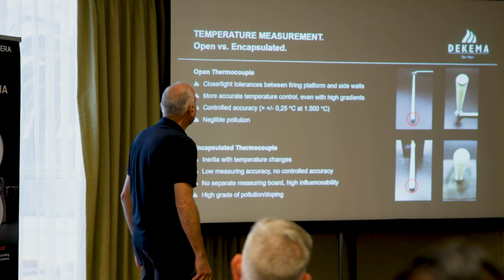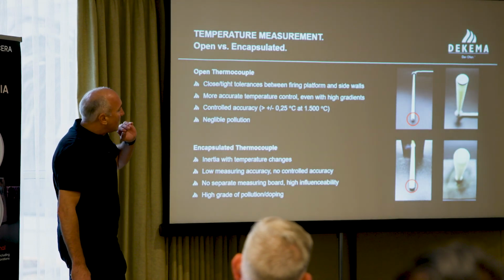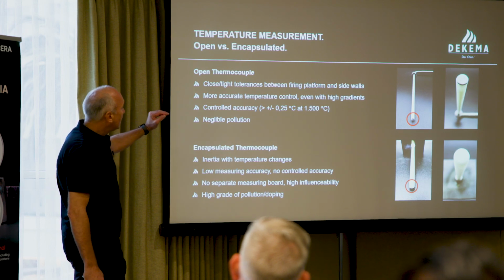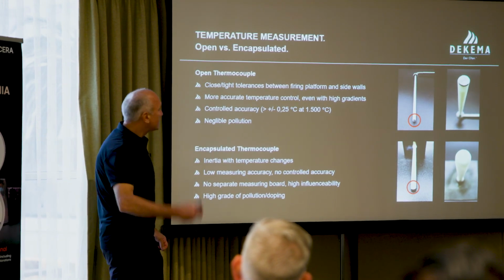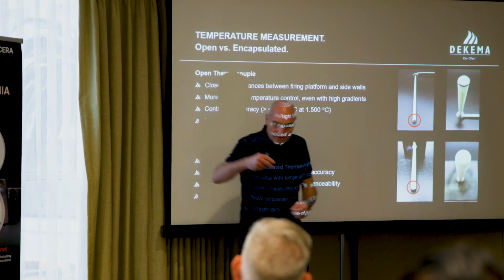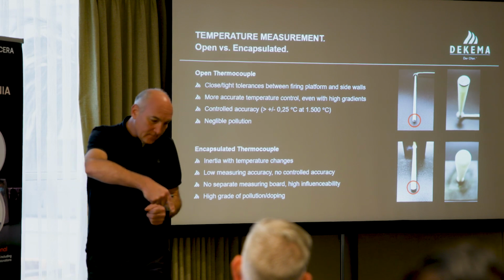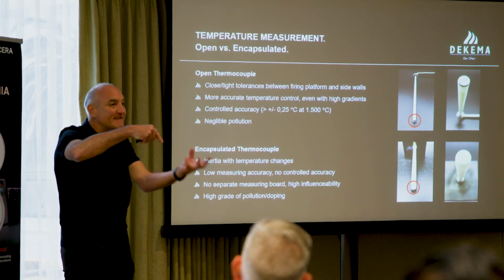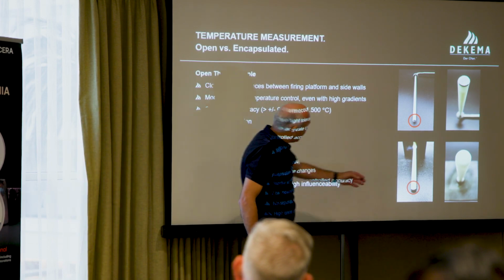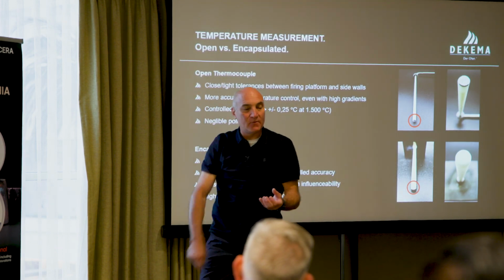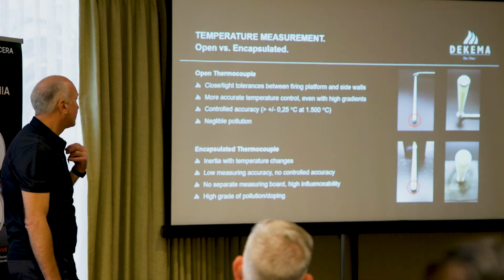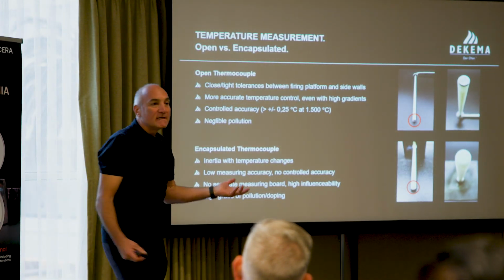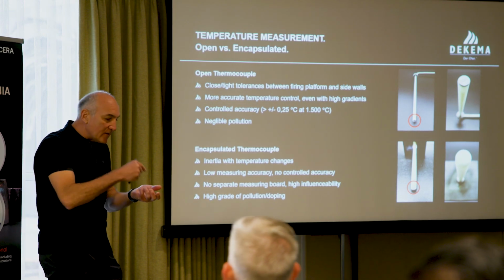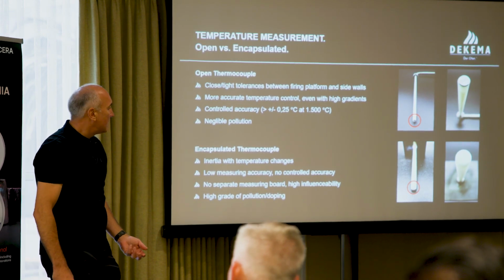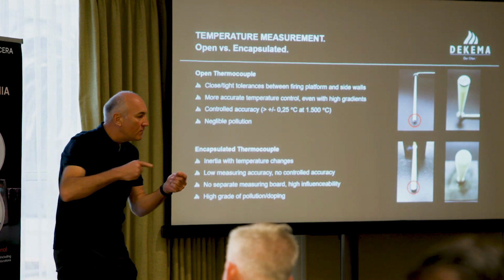And how can you reach that? In the current stage, the final stage, we have a thermocouple. So the temperature measurement with this pin here, which looks directly into the chamber. We don't want the thermocouple to have sunglasses for the radiation. In every other furnace, you have a so-called encapsulated thermocouple. So you have a closed rod, and inside there's this thermocouple wire. What is happening in this case? As I said, it's like sunglasses. You are not looking directly into the radiation you want to see. The temperature always has to go through this alumina rod.